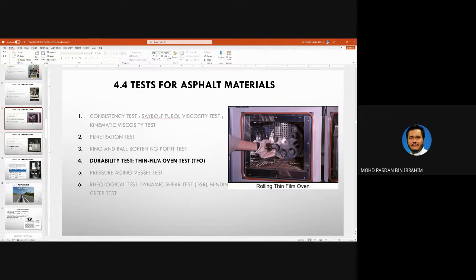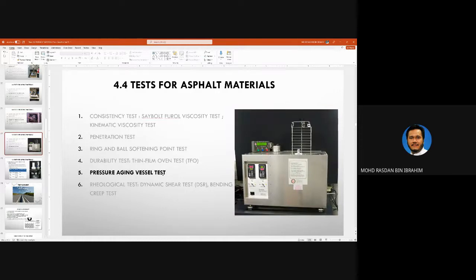The next test is the pressure aging vessel, where you put the bitumen in a small plate and put it in this machine, and they increase the heat and also the pressure. So after the process is finished, the aging that occurs to that bitumen simulates the age of a bitumen of 7 to 10 years. So it's like you are taking bitumen from the site and extracting it from the aggregate of a 7-year-old pavement.